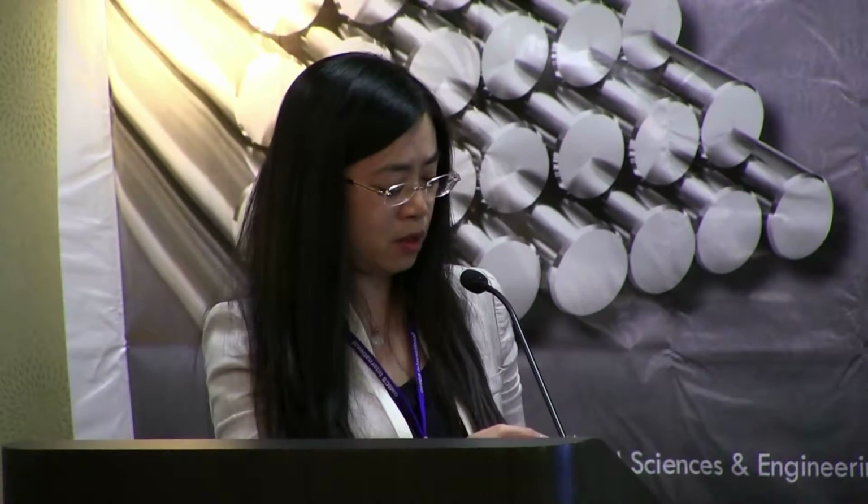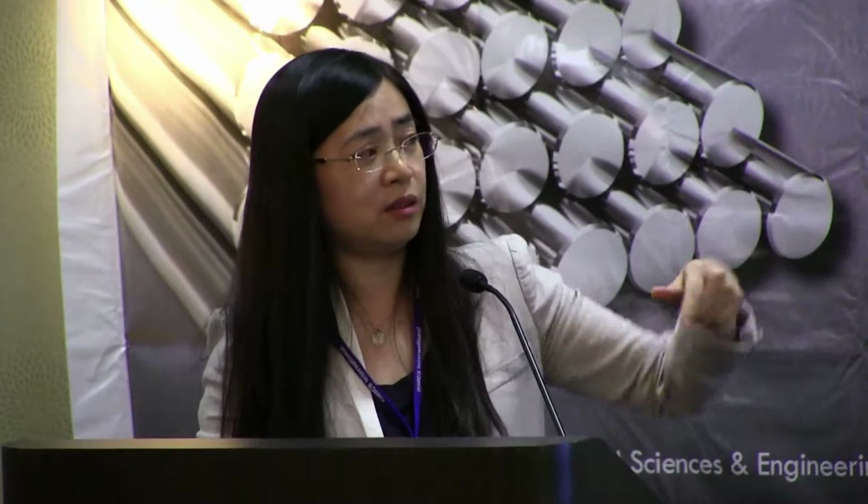Next, we introduce my work in detail. For investigating different sizes, we use different size spindle-knots for water collection, and we found that a larger spindle-knot has stronger water collection. We investigated the mechanism: the uniform fiber and the spindle-knot fiber handle drops differently. We found the spindle-knot holds a larger droplet.